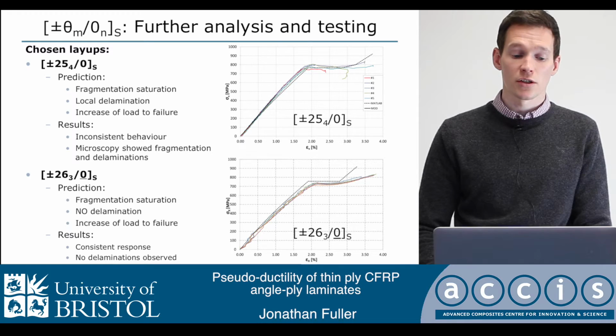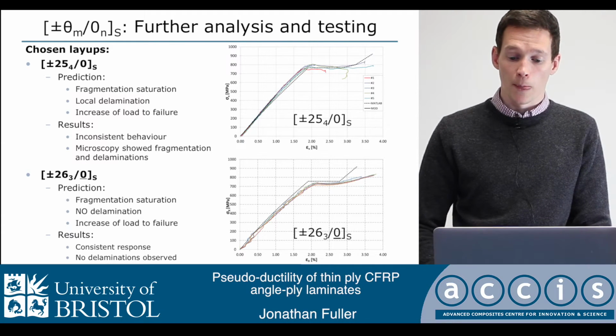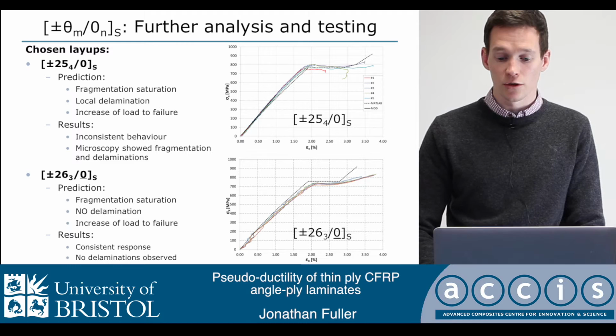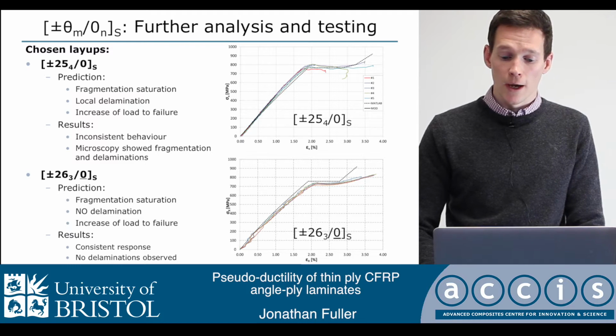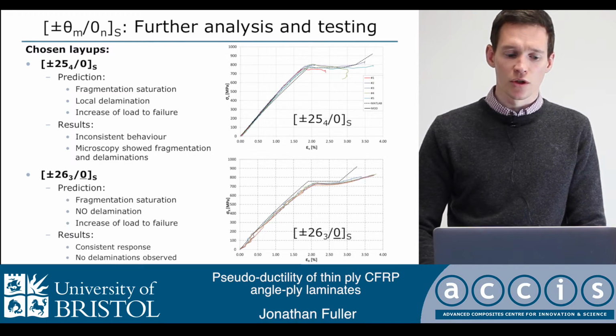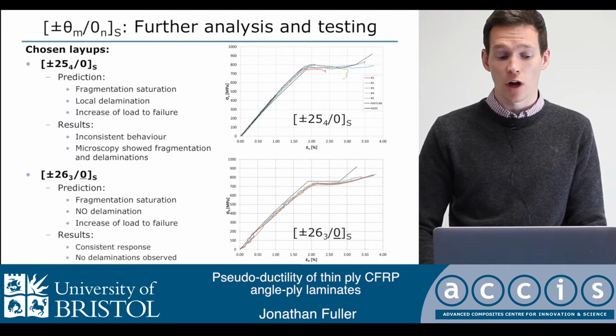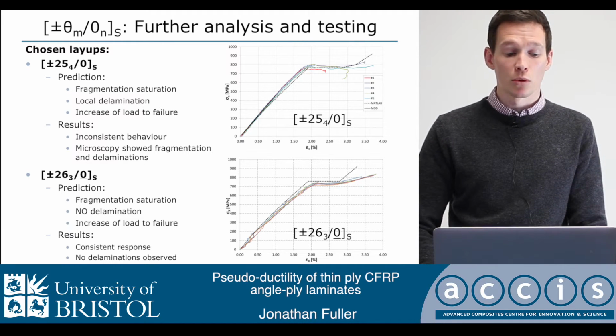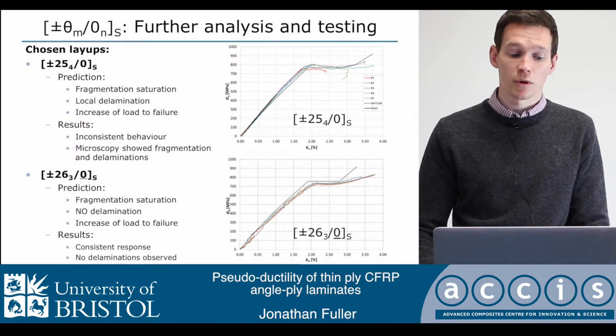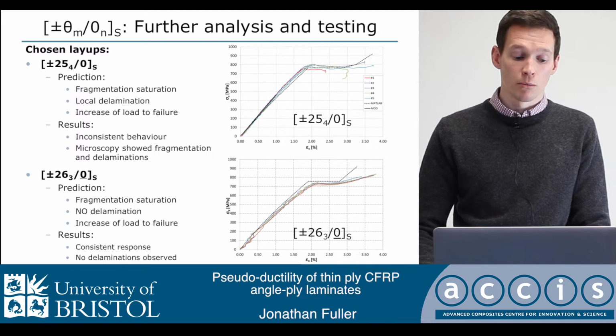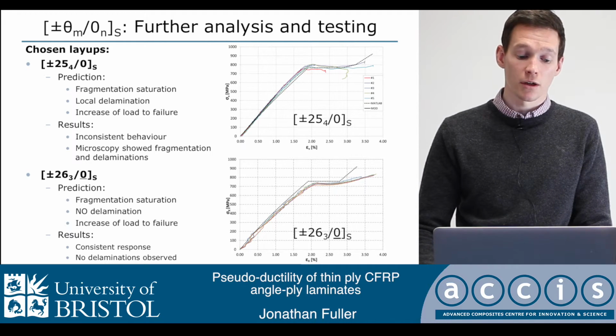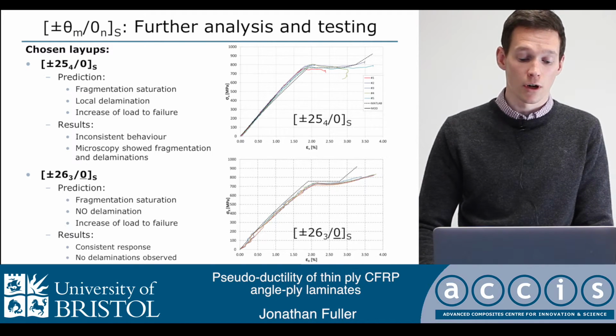So further analysis and testing of these configurations using the analytical model, which is shown in the stress strain curves by the dashed line, shows us that we can have control over not only the fiber angle of the angle-plies, but also the number of zeros at the midplane. So the plus minus 25, 4 pairs with a 0 symmetric, has 2 zeros obviously at the midplane, but the plus minus 26 with 3 pairs only has a single 0 at the midplane, which is denoted by the underline under the 0.